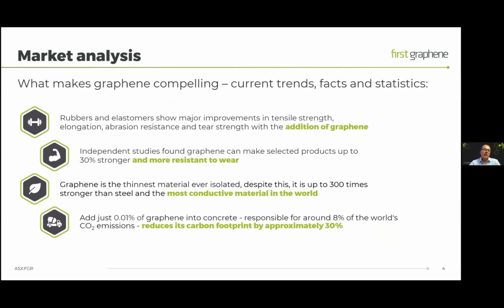So why is that happening? What makes graphene compelling? Well, in rubbers and elastomers and polymeric materials, we see improvements in tensile strength and elongation, durability with the addition of graphene. And there's now multiple studies that show that when graphene is added to these materials, you get typically 30% improvement in mechanical properties such as resistance to wear. Graphene itself, it's the thinnest material that was ever isolated, which is one of the reasons it caused so much scientific excitement and the Nobel Prize. Despite its thinness, it's stronger than steel on a relative basis, and it is the most electrically conductive material that's known.